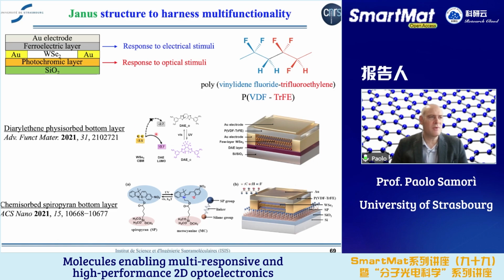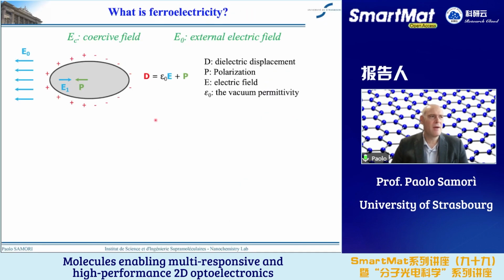So I will show you the details of the first approach. And of course, if the voltage that you apply in the case of ferroelectric materials exceeds the coercive field, the dipoles in the ferroelectric materials partially align with the external electric field, and this results in a permanent polarization. This polarization remains also when you remove the electric field that you apply.